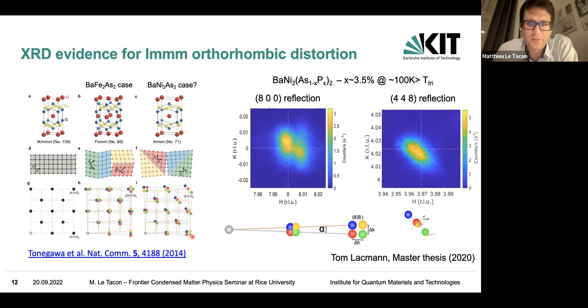And so to see something, Tom Lacmann, in his master's work, basically had to go to fairly high-index reflections. This was done on a four-circle diffractometer, and you see that at around 100 K in this doped system, just above the triclinic transition, the Bragg reflections are not round anymore. You see a fourfold splitting of the 800 reflection, whereas the 488 reflection is now spreading along the diagonal, which is exactly what you expect for this kind of IMMM distortion.